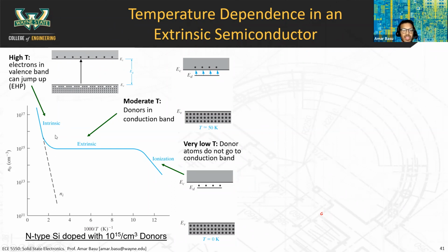This is one of the fundamental limitations of semiconductors, why they can't be used at high temperatures. If you take silicon and you put it up to very high temperatures, like 400 Celsius or 600 Celsius, you're going to start to see this effect where the semiconductor becomes conductive everywhere, and basically it's shorted out. It's just conducting everywhere. So that's not really useful.